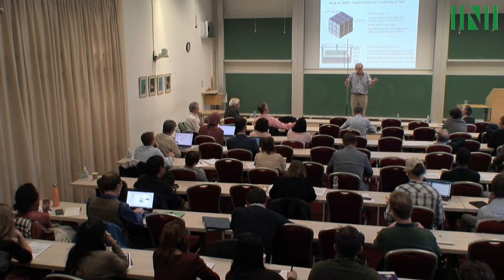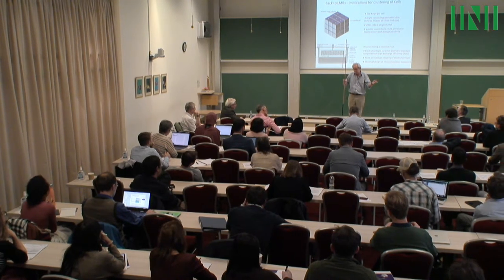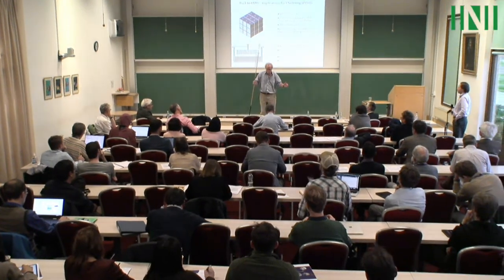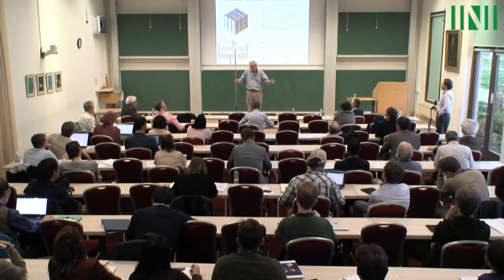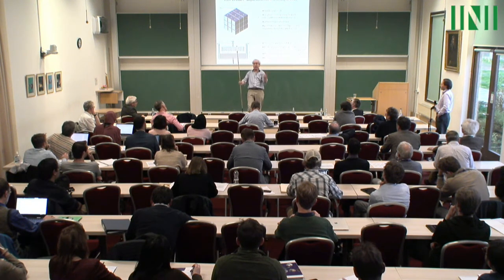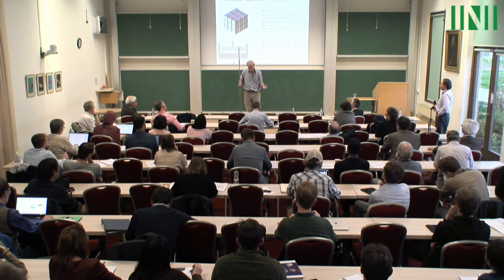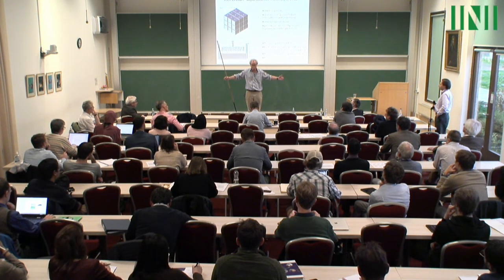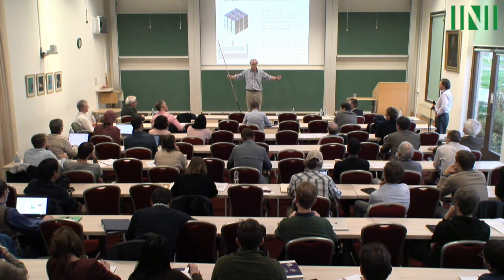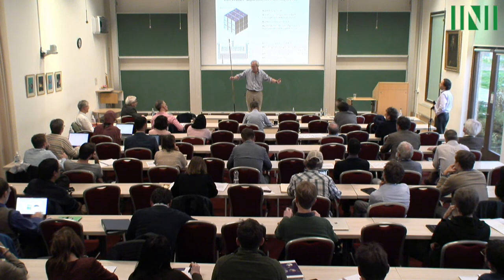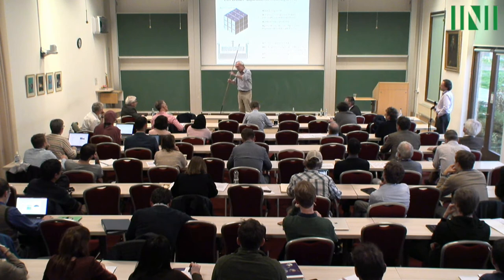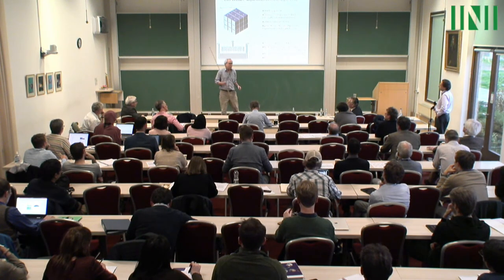It's just like ion reduction cells. Anyone who's worked in electrolysis of aluminium, it's the same thing. The smelter that Don showed, they operate wonderfully smoothly. You walk into a smelter, you get hit by the heat because of all the ohmic heating of the electrolyte, but it's very quiescent. You've got all these cells sitting there just humming gently, and everything seems fine. But it took the aluminium industry a phenomenal amount of time to get there in terms of thermal design, aspect ratio, flow of current, electrical connections between individual reduction cells, and so forth.